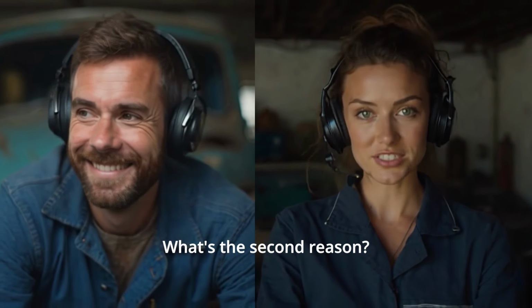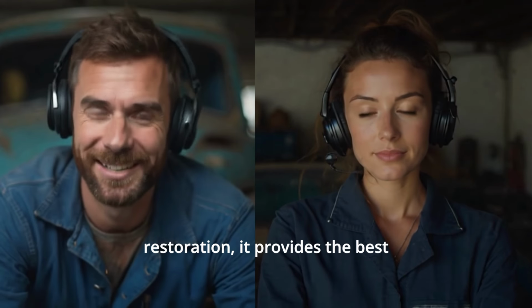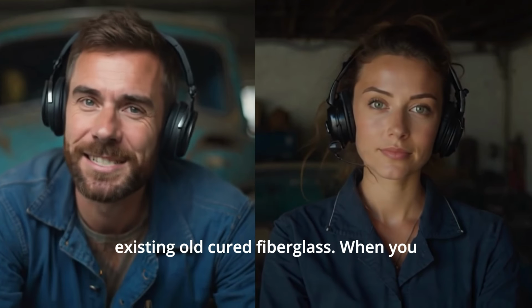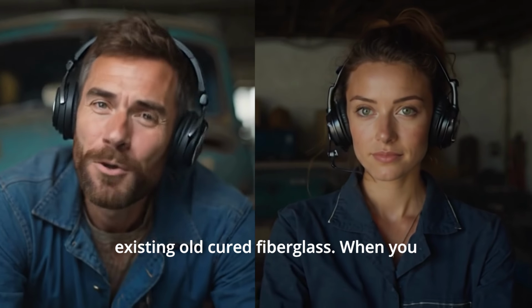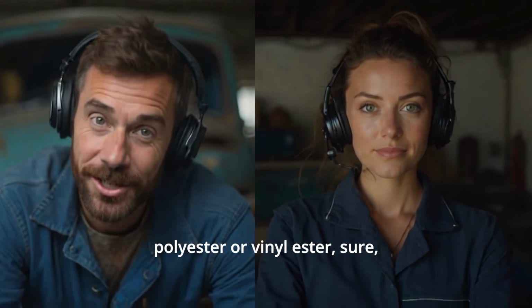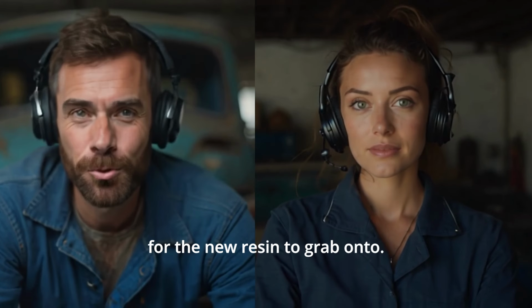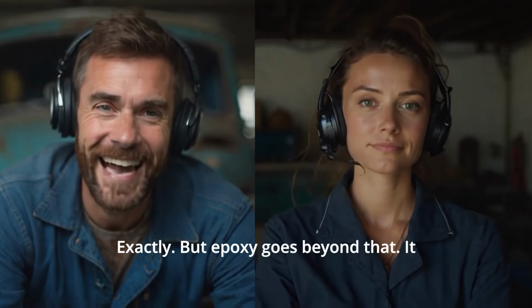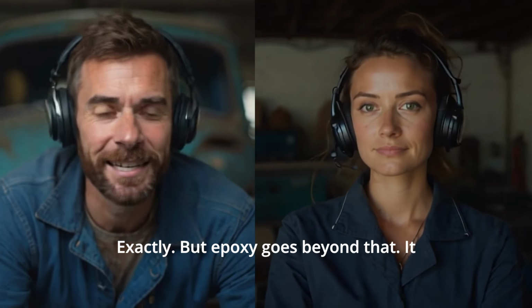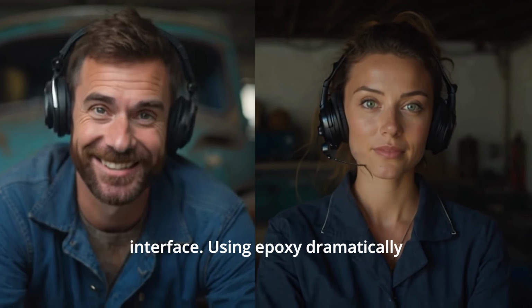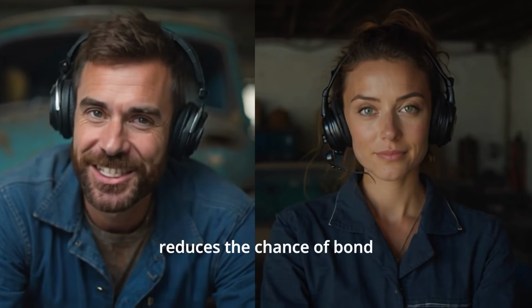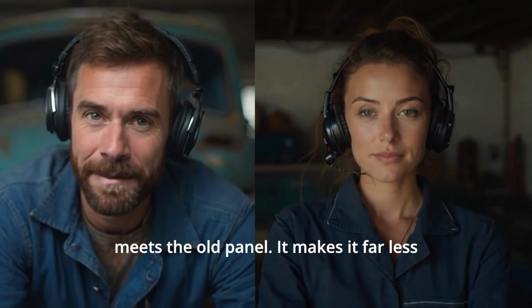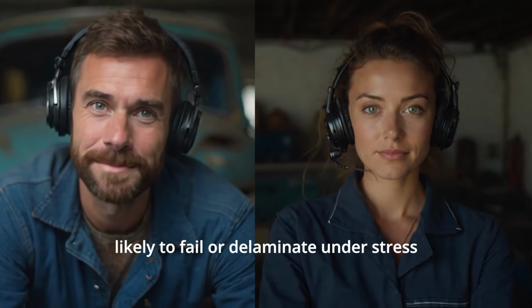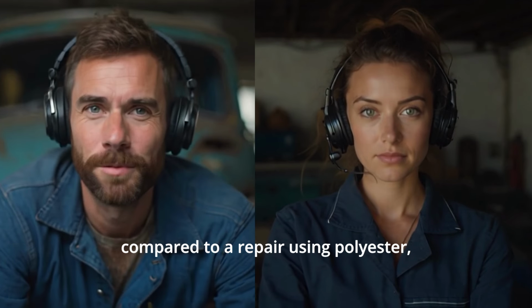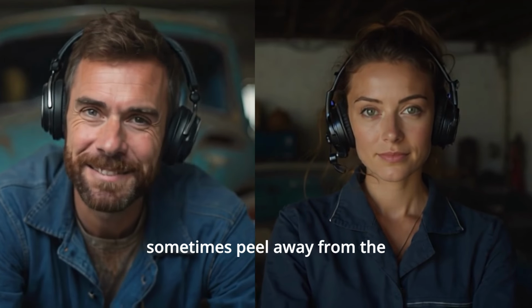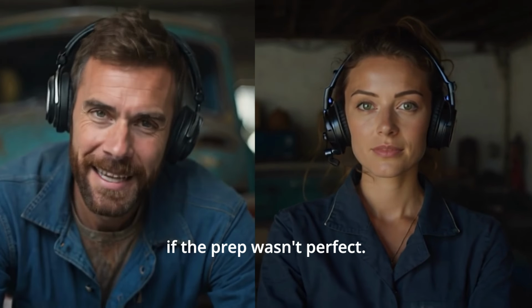Okay, minimal shrinkage. What's the second reason? Second, and this is critical for restoration, it provides the best chemical adhesion to existing old cured fiberglass. When you grind down old polyester or vinyl ester, sure, you create a mechanical key for the new resin to grab onto. Right, like roughing it up. Exactly. But epoxy goes beyond that. It creates a much stronger chemical bond across that interface. Using epoxy dramatically reduces the chance of bond failure where the new repair meets the old panel. It makes it far less likely to fail or delaminate under stress compared to a repair using polyester, which honestly can sometimes peel away from the old substrate over time if the prep wasn't perfect.